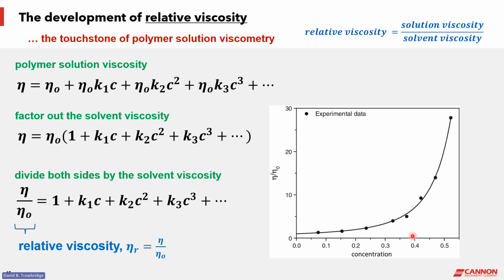And you can see the dramatic increase as concentration increases. We have this curvature because of the higher order terms being dependent on powers of concentration. We see that kind of growth. If we work at lower concentrations, this term will become less significant. If the concentration is 0.1, cubing that is 0.001. So this term can get small when we go to low enough concentrations. And in fact, we do that, and we're left with an equation now that's just truncated at this term, and this becomes the working equation going forward, and the graph becomes much more manageable. You can see it shown here.